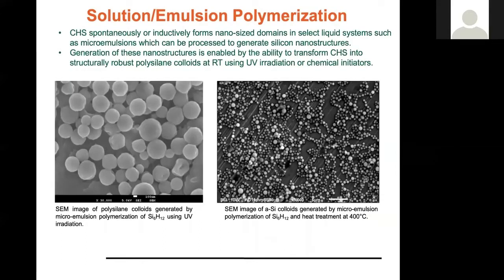Another thing that's unique about CHS is that it's a liquid at room temperature, unlike monosilane or many of the commercially available silanes, so it can be processed in solution. You see here some micrographs of polysilane colloids, as well as amorphous silicon colloids, generated from reaction in solution, either thermally or by ultraviolet irradiation. We have very good size dispersion and fine control over the particle morphology as well.